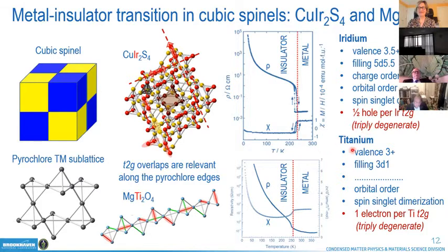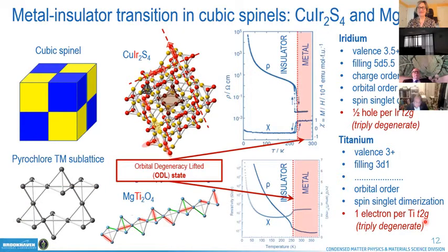On the other hand, titanium is always in valence 3 plus, and it has a filling of d1. There is no charge ordering, as opposed to the iridium case, where there is charge disproportionation taking place at the transition into 4 plus and 3 plus species. There is orbital order, spin singlet dimerization, and as I said, there is 1 electron per triply degenerate titanium t2g. Okay, so in what follows, I will show you that the high temperature regime can be regarded as an orbital degeneracy lifted regime, in some sense similar to what I have shown in manganites.